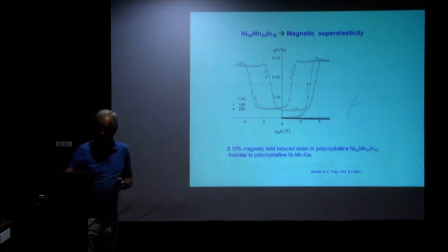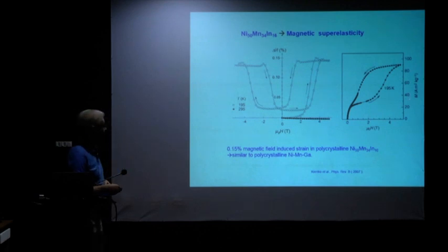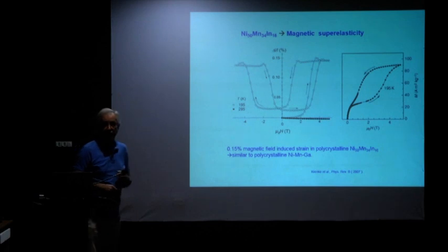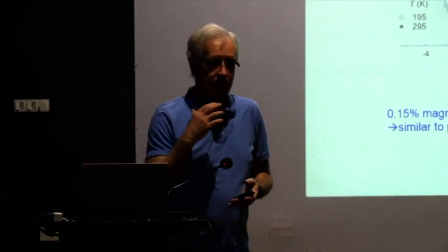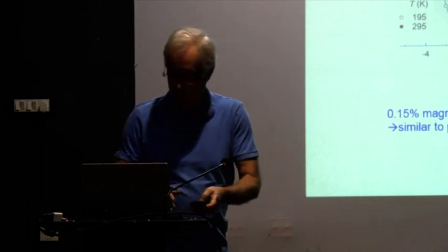And when we look at the magnetization, here we see the field-induced transformation. We go up, this goes to about 5 Tesla, same as this field over here. And as we decrease the field, this goes back down. So the strain measurements, what do they give us? They give us information on what is happening to the length change, and we see here that everything follows more or less the magnetization. The strain is related to the magnetization almost directly. Now we'll come to some strain measurements.